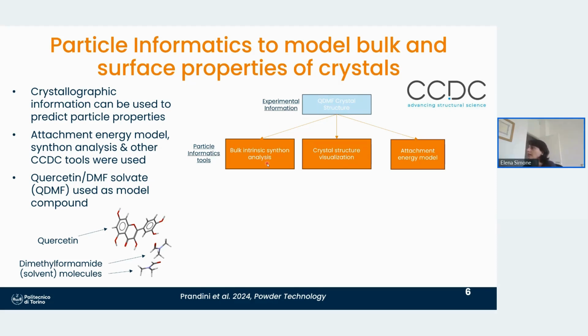This is normally quite useful also to see how the molecules are arranged. And then we did a bulk intrinsic synthon analysis. So we calculated the main intermolecular and intramolecular interactions within a specific volume of our crystal structure. Then we applied the attachment energy model, which basically ranks which specific synthon contributes to the growth of the different facets. So then we can understand a little bit the nature of the different facets, so whether they grow via hydrogen bonds or pi-pi stacking and so on.